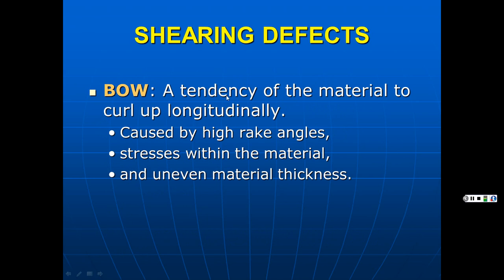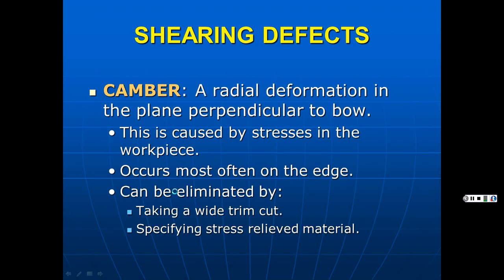A bow, like we said, a tendency of the material to curl up longitudinally, like the bow of an arrow. Caused by high rake angles, stresses within the material too. Like you can cut something and because the material wasn't stress relieved, some of the metals, once you cut it, it throws it out of whack, and then it bows up. And the material thickness may not be even all the way around. Camber, like we said, the radial part where it's curving out, a radial deformation in the plane perpendicular to the bow, so kind of like the width versus the thickness.